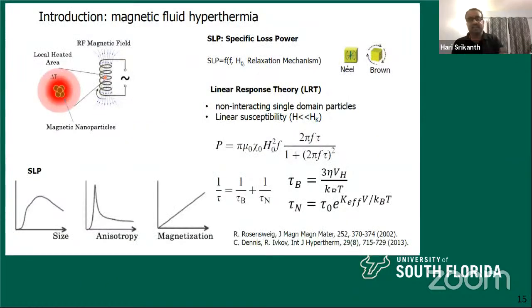Okay, so here's another slide. Again, I won't spend too much time. The power loss can be calculated, and you can see that it's a product of the AC amplitude and the frequency. So that's what is important here. And there are two different time scales involved. These are relaxation times. One is the Brownian, the other one is the Néel relaxation time. So it's a combination that matters. And essentially, SLP is the same as SAR. Some people call it specific loss power. You can see that if you increase the magnetization of the nanoparticles, then the SAR will go up. Remember, our goal is to maximize the SAR as much as possible.